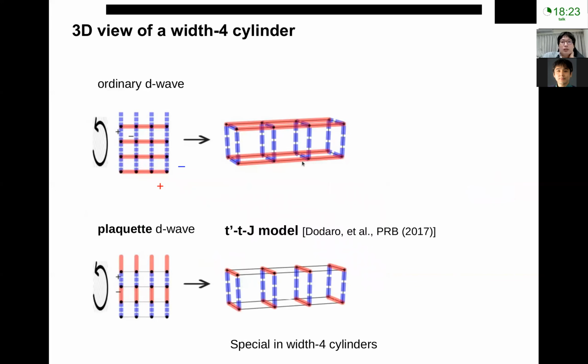But then we understand that this correlation is also not so surprising, because a width-4 cylinder is a very special geometry. If you look at this from a more 3D point of view, a width-4 cylinder means you have only 4 sites in one direction with periodic boundary condition, so you wrap around these 4 sites, and you find this width-4 cylinder is actually just a stack of plaquettes, like a chain formed by a series of plaquettes.